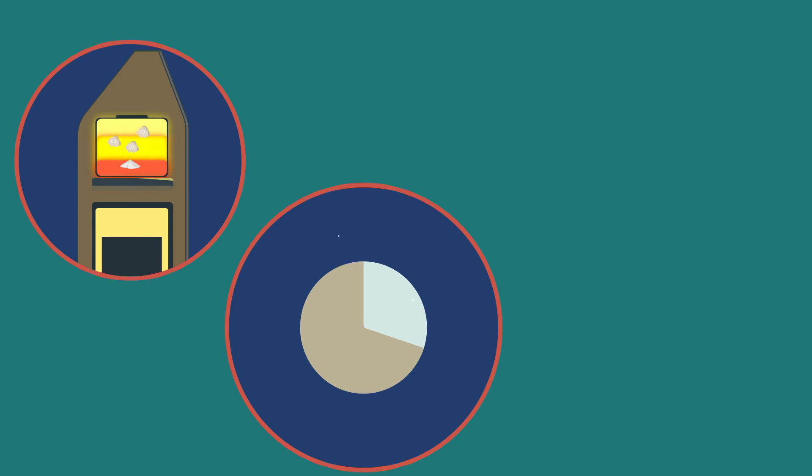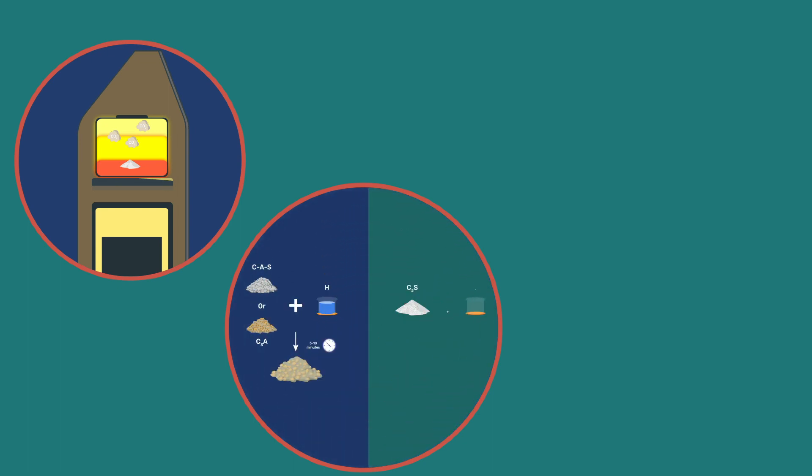In conclusion, natural cements rely on selecting a single rock as starting material. Their calcination produces a combination of aluminates and silicates that are respectively mainly amorphous and crystalline. The aluminates are responsible for the fast setting and early strength, while the silicates deliver the final strength, but on a much longer time span, typically several months.